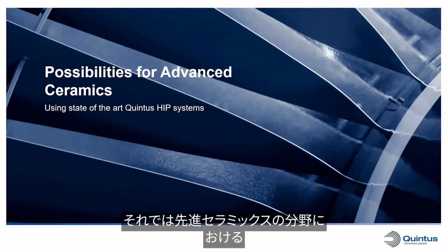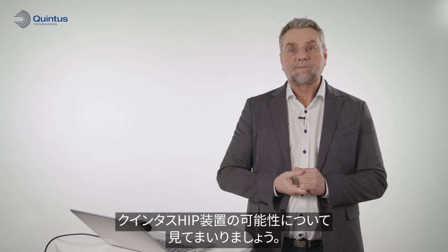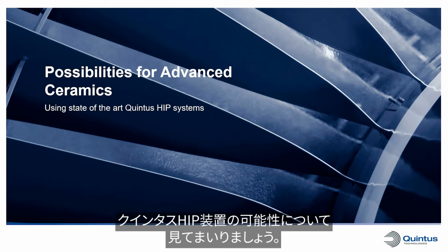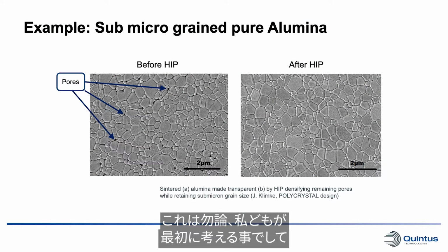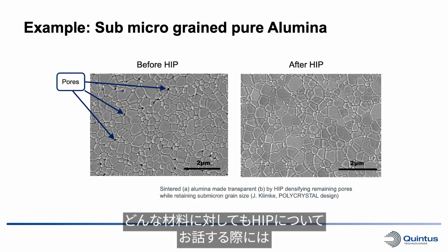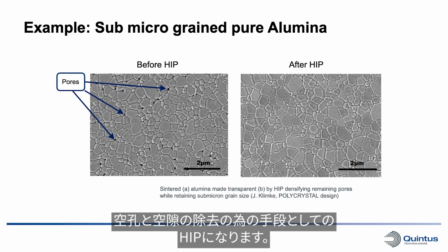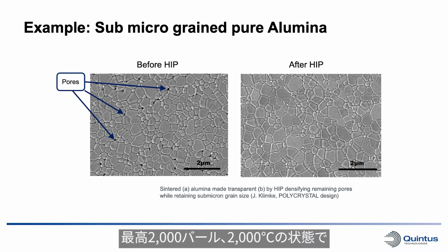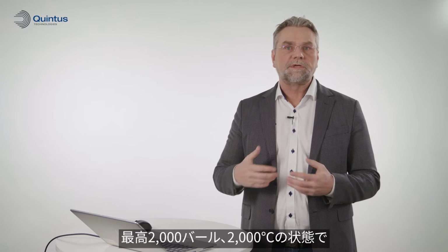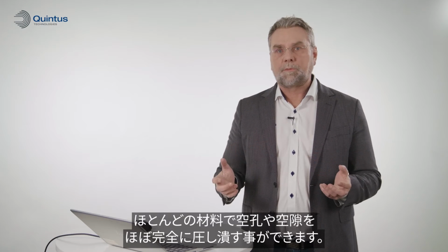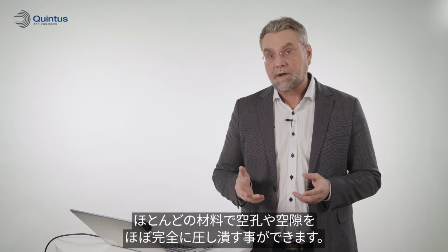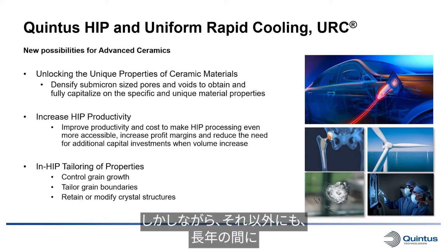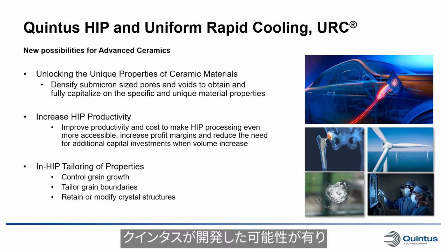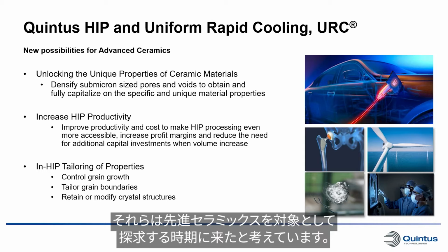So let's start exploring what possibilities Quintus HIP systems bring to the field of advanced ceramics. This is, of course, what we firstly think about when we're talking about hot isostatic pressing for any material: when we want to remove pores and voids, we go for hot isostatic pressing. We can use up to 2000 bars, 2000 degrees centigrade, and close most any pores and voids in most any material. However, there are other possibilities that Quintus has developed over the years, which we now think it's time to also explore for advanced ceramics.